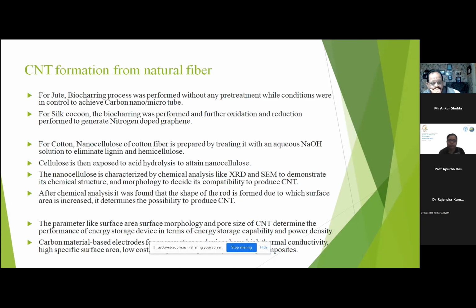If we take a cotton fiber, then nanocellulose of cotton fiber is prepared by treating it with aqueous sodium hydroxide solution to eliminate the lignin and hemicellulose part. I already discussed how to eliminate lignin and hemicellulose. That cellulose is then again exposed to acid hydrolysis to attain nanocellulose.